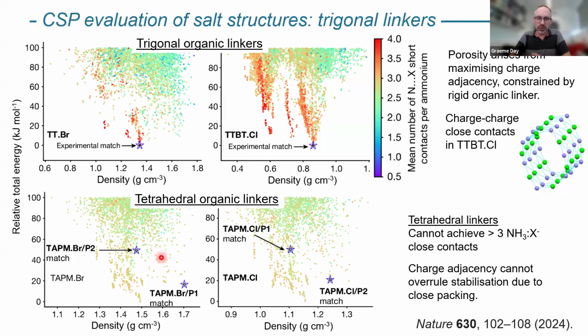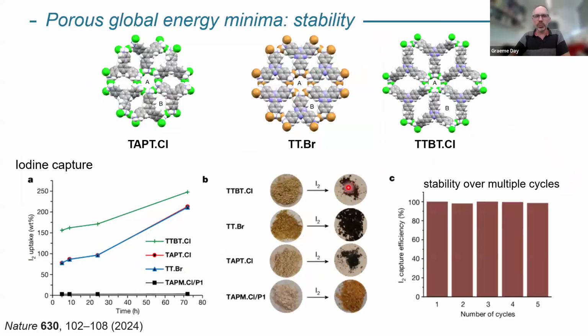Whereas the system I showed you that didn't work, what you see is that you can't get beyond about 3 contacts, whereas it seems that you need about 4 of those contacts between a chloride and an amine to get the stabilization you need to stabilize these porous structures. So again, we're learning more and more by analyzing these landscapes. You get useful properties as well. Here's something we looked at was getting iodine in and out. We can cycle this in and out and you can see it nice and visually, the material goes dark.